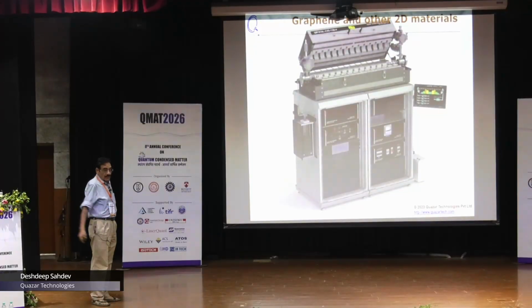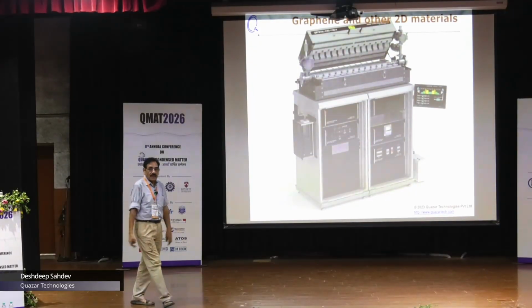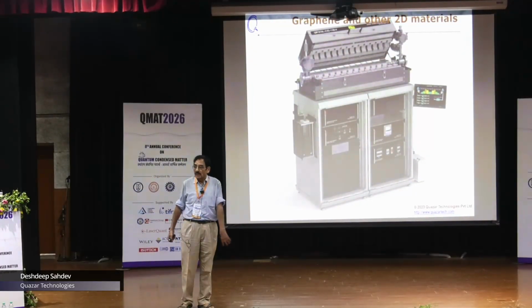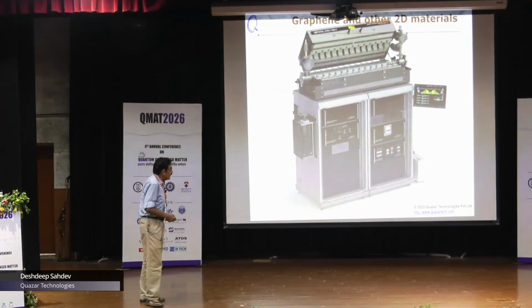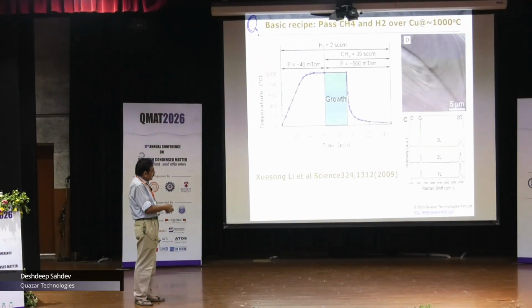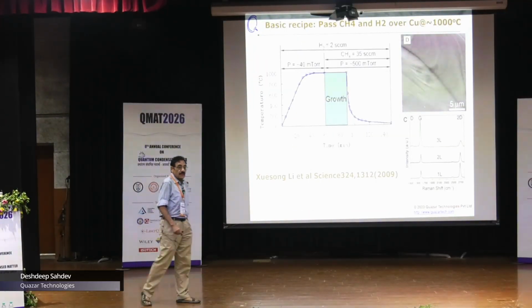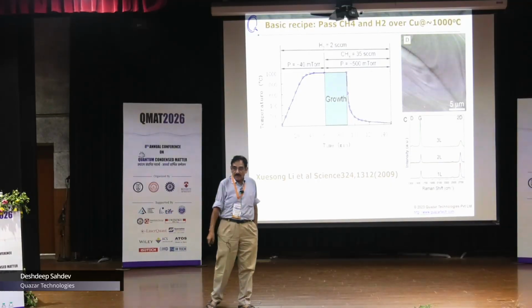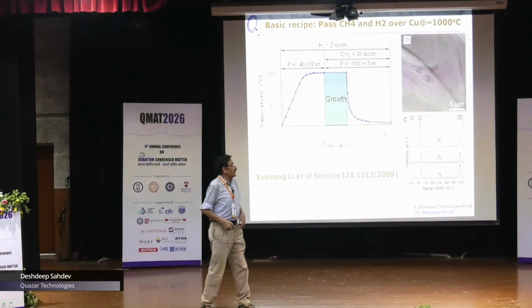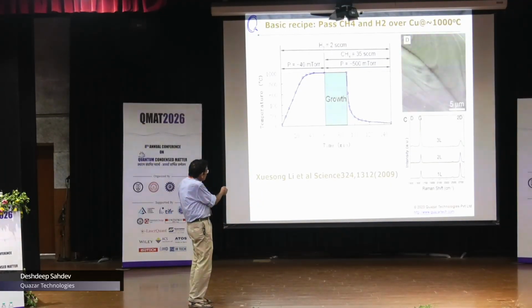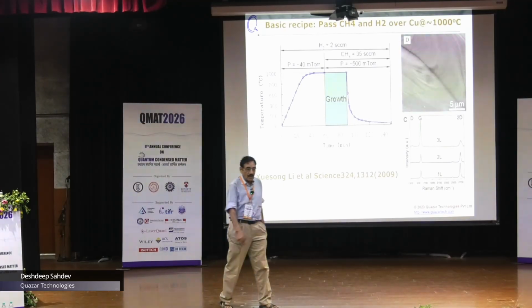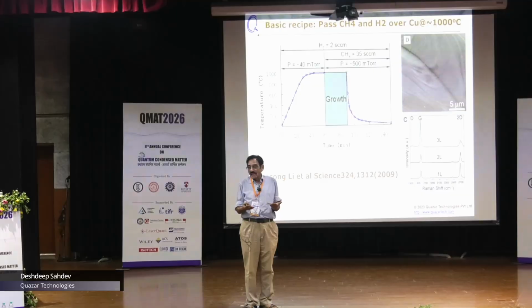And then the next thing, of course, if we had to close this loop, we had to be able to make samples and so on. So we built a high-end CVD system. And one of the things that we did with it initially was to grow graphene. And the way you grow graphene is this. You just pass methane and hydrogen over copper that you heat to about 1,000 degrees, all right? And then when you cool it down, the graphene just forms on top of it, all right? We won't get into how, but it just does, all right?